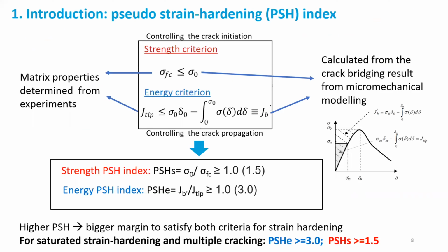To further quantify the two criteria, we introduce the so-called pseudo strain hardening index, PSH index. The first one, the strength PSH index, PSH_S, equals the fiber bridging strength over the first cracking strength of the matrix. And we also have the energy PSH index, PSH_E, which equals the maximum complementary energy over J tip of the matrix. Theoretically, the values for both indices should be higher than 1. However, as reported by researchers, in experiments a PSH_S value of 1.5 and a PSH_E value of 3.0 is more beneficial for robust strain hardening behavior to happen.